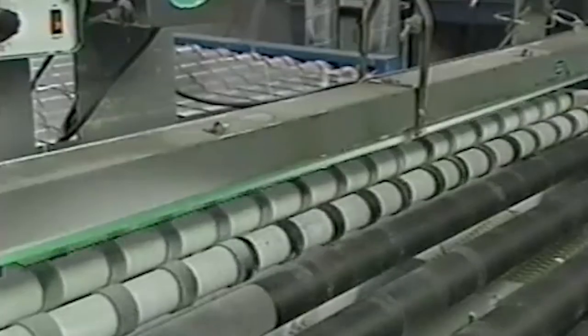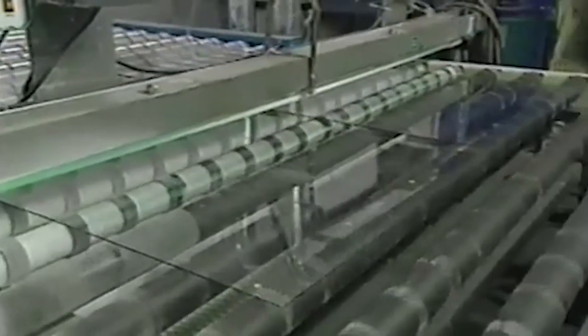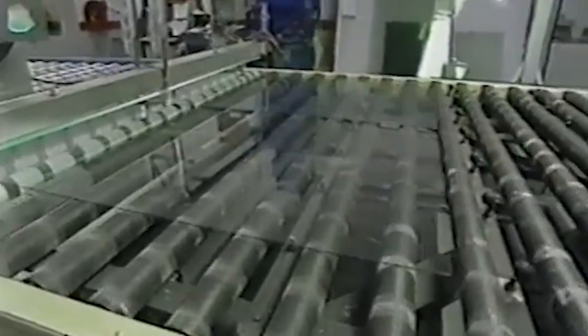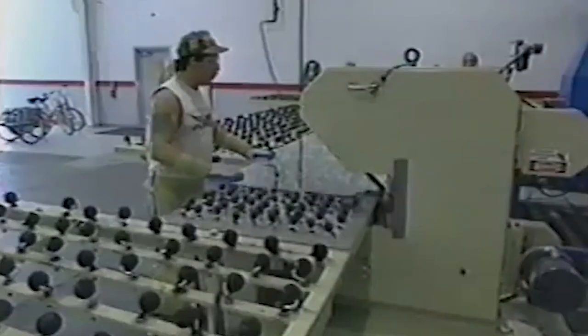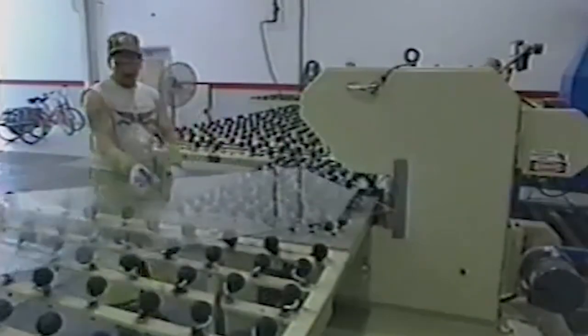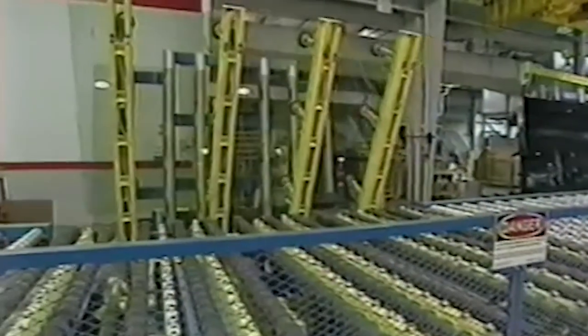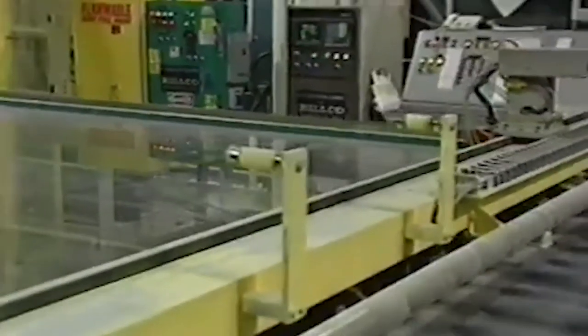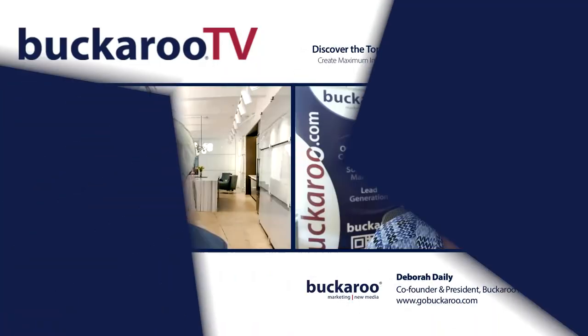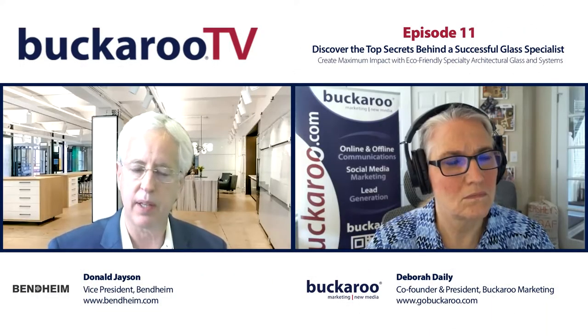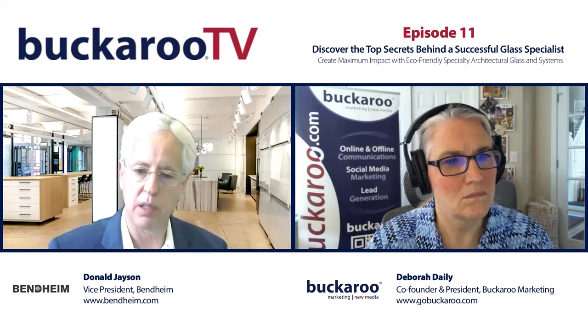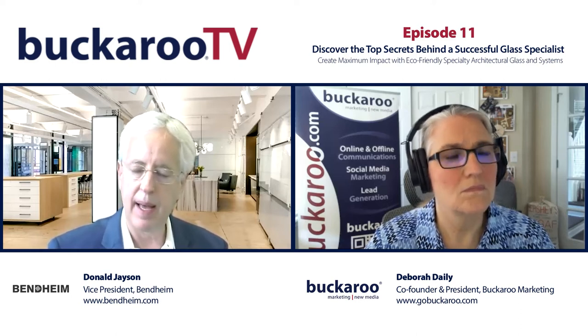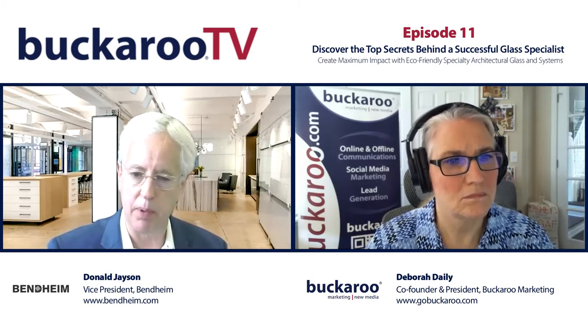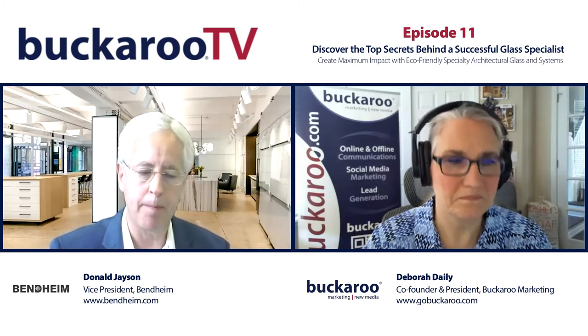So tempered glass is we take annealed glass and it goes into a furnace, which we call a tempering furnace. And it goes on to oscillating ceramic rollers, and the glass gets heated to 1100 degrees Fahrenheit or 600 Celsius. And when it reaches that temperature, it gets transferred into another section of the oven, which is called the quench. And in a quench, it gets cooled very rapidly with air. And during that process, it forms a compression strength in the glass. And the glass is four times as strong as it was before it was tempered. And if it breaks, it dices, it crumbles, like your car side window. I don't know if you've ever seen that break, but yeah, it crumbles.